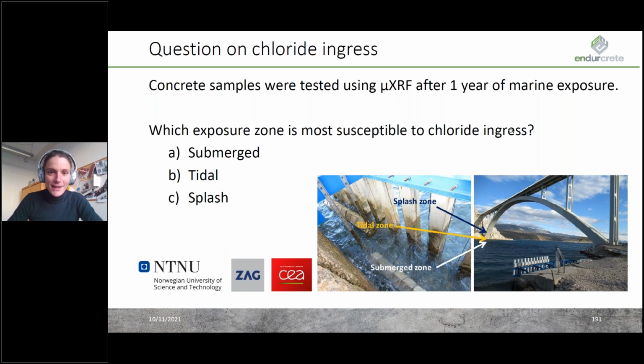And if our EnDurCrete concrete is supposed to be durable, it has to have good resistance against chloride ingress. So I just have a couple of slides where I'm going to take some examples, and we're going to look into the concretes which have been exposed at the Kirk exposure site, which Irina already introduced to us. We scanned these with a micro-XRF after they had been exposed for 1 year.